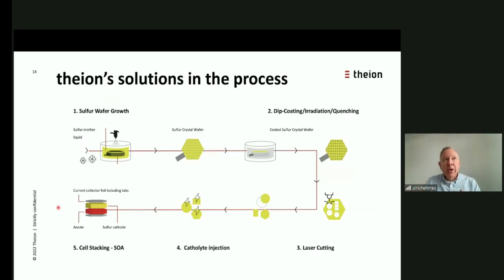And I will show you how we process the sulfur in order to come to this high energy cathode. So what we are doing is melting down sulfur at 125 degrees. Then we spray a very thin layer of carbon nanotubes on top of this, less than 1 weight percent, highly conductive for heat and currents. And then we apply 60,000 volts and all these particles get lined up like nanowires on top of the molten sulfur. And then we crystallize the sulfur around these carbon nanotubes. And this is a self-standing cathode made out of crystals without any binder and a very, very high active material content. And this is the base for our cathode.